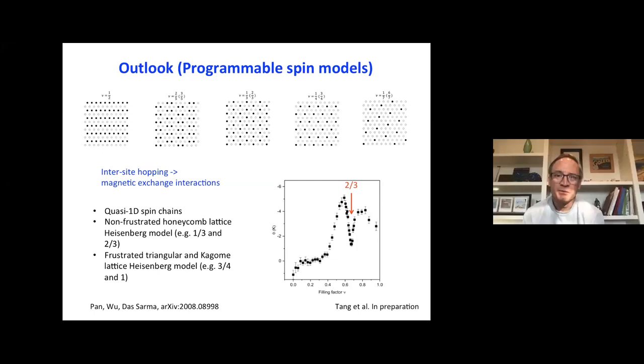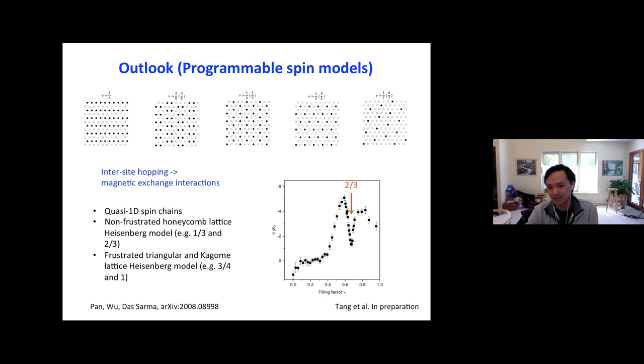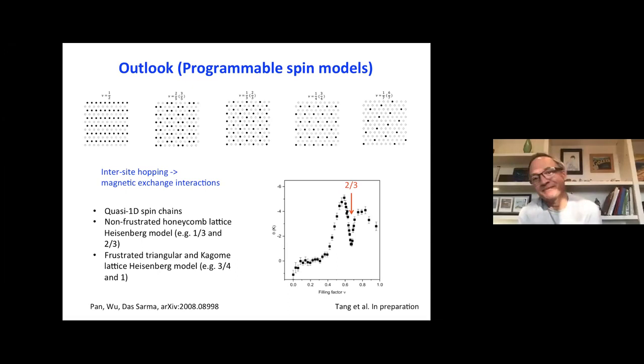But usually Pauli susceptibility is smaller, right? I mean, the denominator in the Curie-Weiss law is something like J, which is T squared over U, whereas in the... Yeah, in that sense, we just did not see any Pauli-like behavior in this system. At least for filling factor below one, we always see Curie-Weiss behavior in the high temperature limit. Yeah, that's interesting.